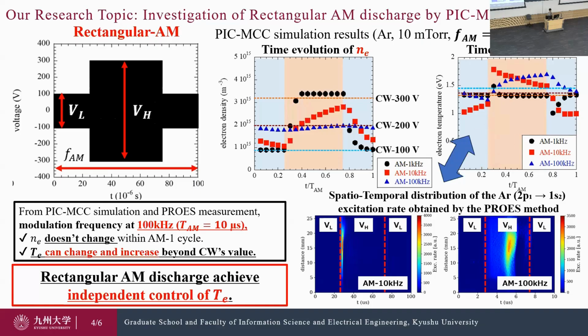The increase in electron temperature at the rising edges of the rectangular amplitude discharge was also observed in PROES measurement using an ICCD camera, showing good agreement with the simulation results. These findings suggest that rectangular amplitude modulated discharge enables partially independent control of electron temperature.